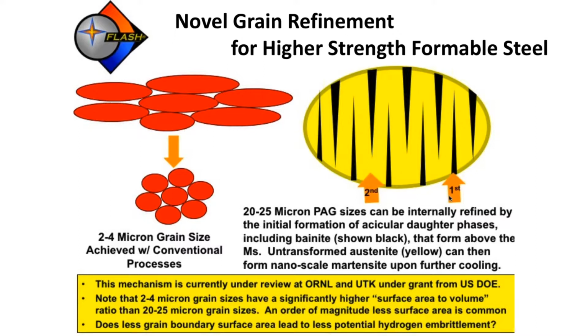And while it's interesting for us to say that, we've worked with a couple major steel mills. One of them in particular has a continuous annealing line simulator. We gave them a full sheet of flash bainite raw material. Half of it was processed into flash bainite. Half of it was left as 1020 steel. The parts that we had processed were easy to show 1500 megapascal UTS and good elongation and an 80% yield to tensile ratio, so 1200 megapascals yield.